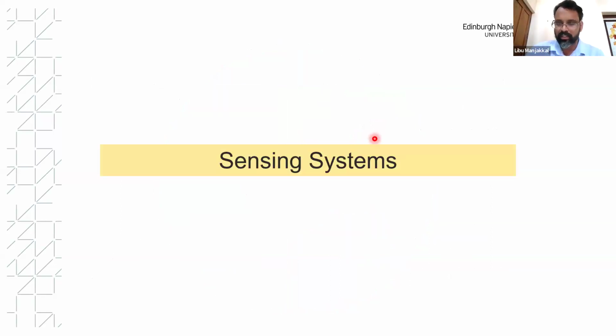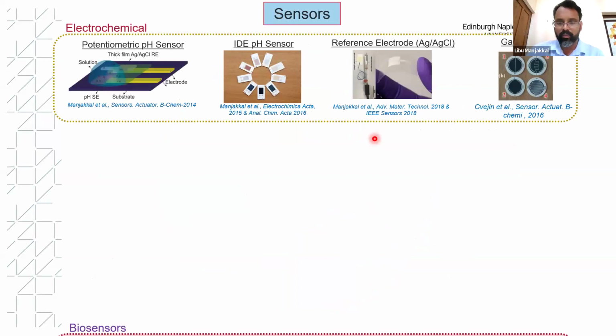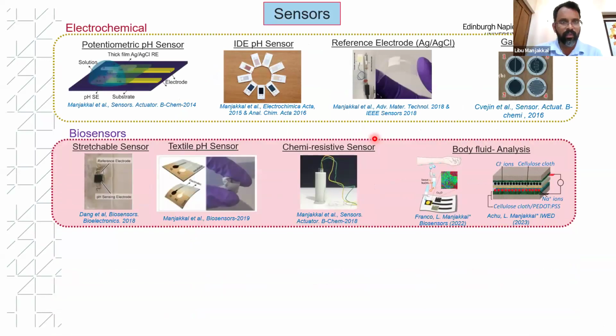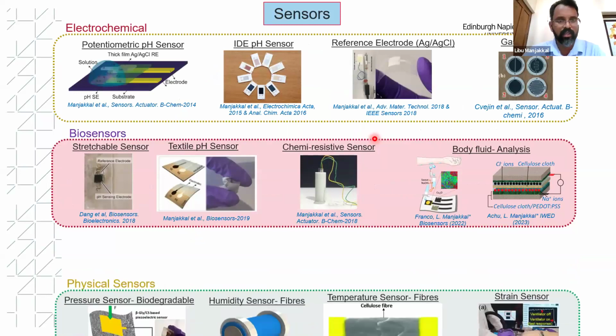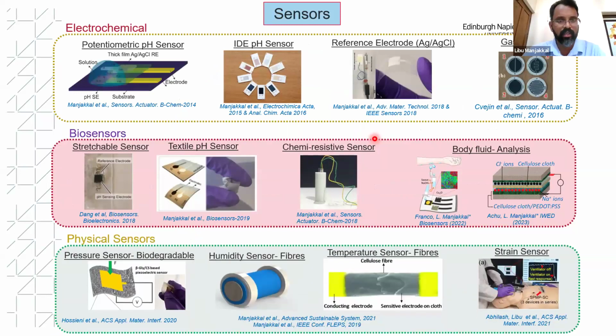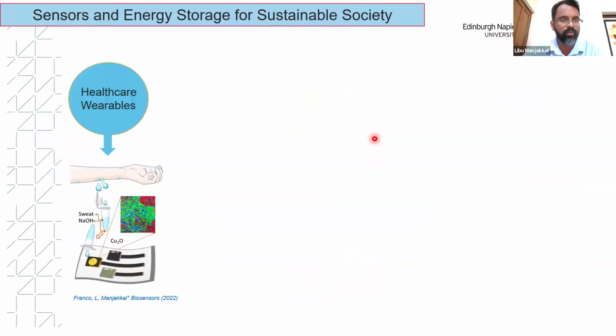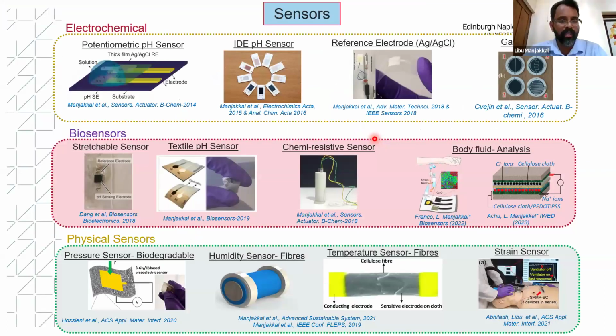One is the sensing system. Here you can see some of the sensors which I already developed in Poland. One of the major areas where I did my research work is electrochemical pH sensor development, especially on a thick film substrate like an alumina substrate or any other substrate, where I developed my own sensitive material and also a thick film reference electrode based on a silver chloride and glass composite.